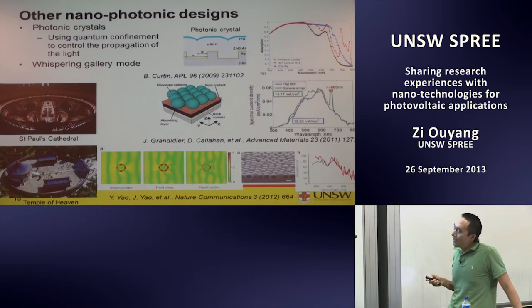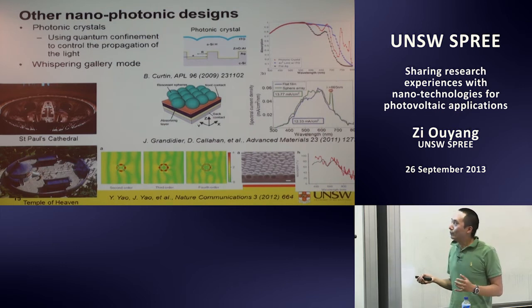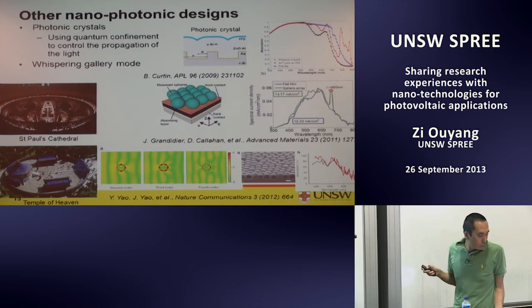So people, smart guys, have this idea, and they think, oh, why don't we use this mode on solar cells? So they developed these resonant spheres. The light, once it gets in, will bounce back and forth inside and will not escape, unless it is at the point adjacent to the absorbing layer. So it's like an integration sphere you use for your transmittance, reflectance measurement of your sample. You can consider it as a detector underneath. Every time it goes down, it will absorb a little bit. Every time it goes down, absorb a little bit, because if you make the spheres very little absorbing, you can actually have very high absorption in the absorber layer you want.